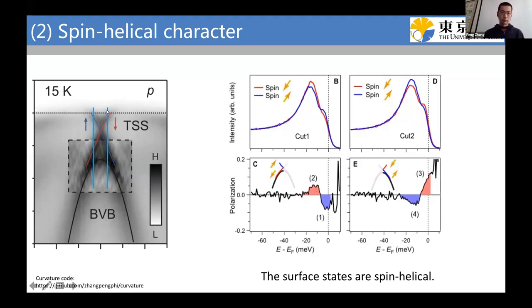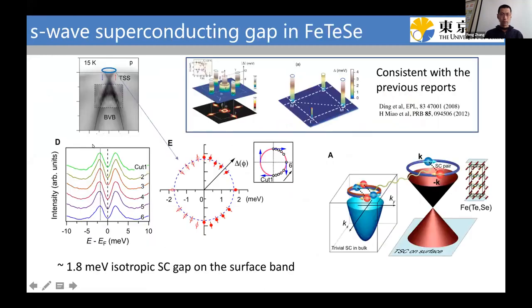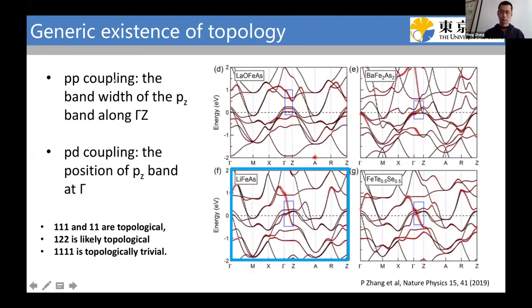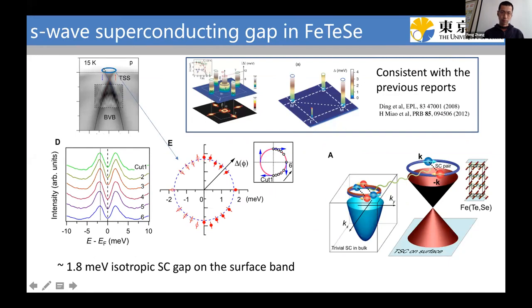So this is consistent with the spin polarization of the topological surface state, confirming its surface nature. The last piece for topological superconductivity would be the S-wave superconducting gap of the surface state. This should be easy to understand, since we know that iron-based superconductors have an S-wave gap in the bulk, so the surface should naturally also have an S-wave gap. Indeed, we focus on this small surface, and we observe no obvious anisotropy for the gap. Then we conclude from the Fu-Kane model that the surface of iron-based superconductor is topologically superconducting.